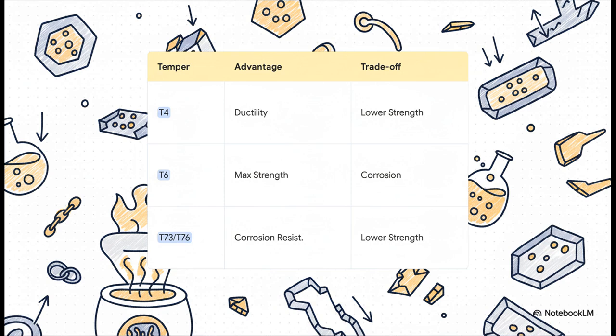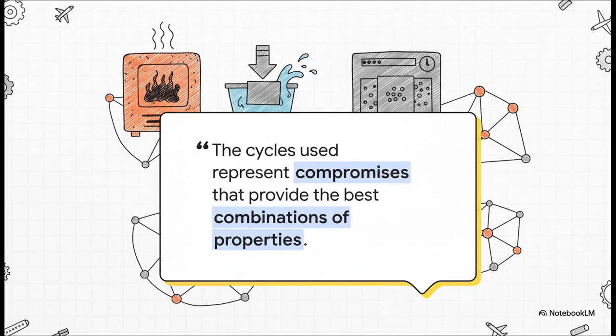A T4 temper, for instance, is more flexible, which is great, but it's not as strong. A T6 temper gives you that maximum eye-popping strength, but it might be a little more vulnerable to corrosion. Then you have tempers like T73/T76, where you actually sacrifice a tiny bit of that peak strength in exchange for amazing resistance to cracking under stress, something that's absolutely vital for an airplane wing. And this quote from our source material just nails it. It's not about making something as strong as physically possible. It's a science of carefully engineered trade-offs, all to get the absolute best combination of properties for whatever you're building.